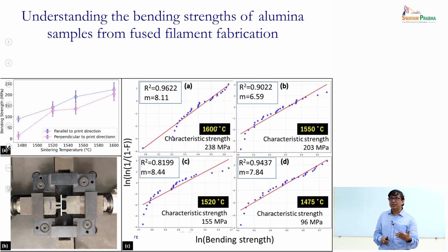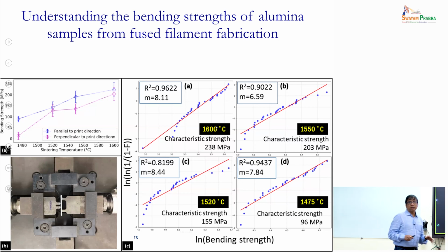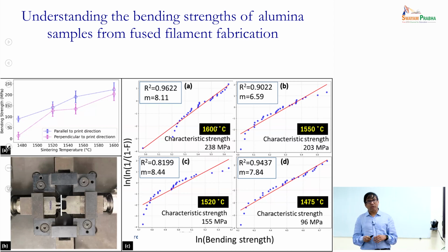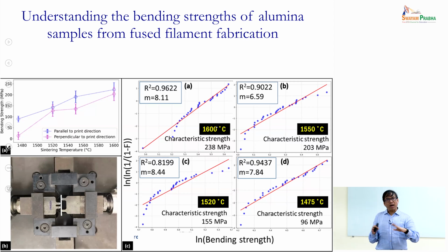So a higher Weibull modulus means a narrower strength variation and less sensitivity to flaws, because ceramics are very, very sensitive to flaws in the samples. With more flaws, the probability of failure is high. Therefore, when you get a higher Weibull modulus, that means the ceramic microstructure you have, and the manufacturing technique you have adopted, is less sensitive to flaws. I think this is part of the tensile, compression and bending story of ceramic parts in general.